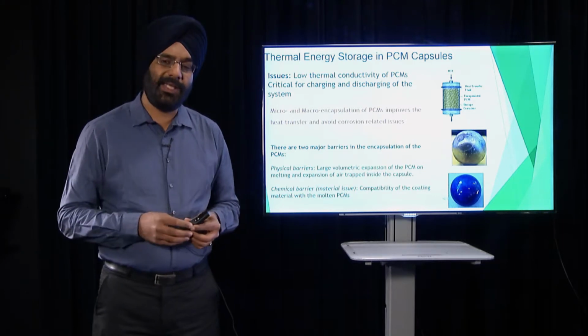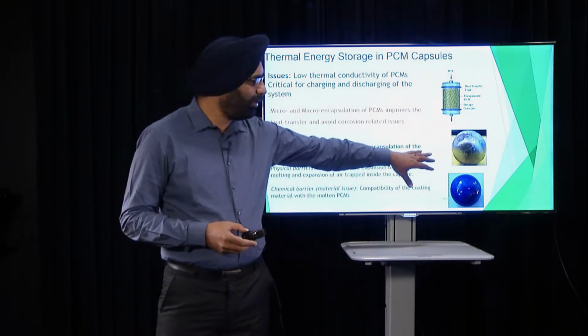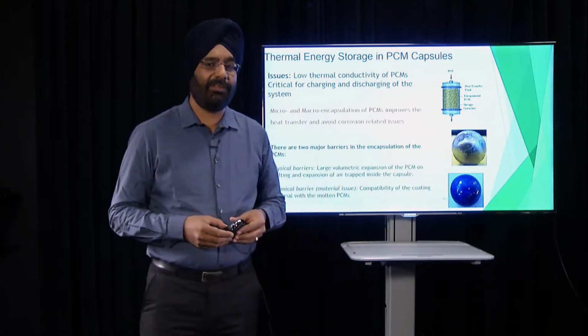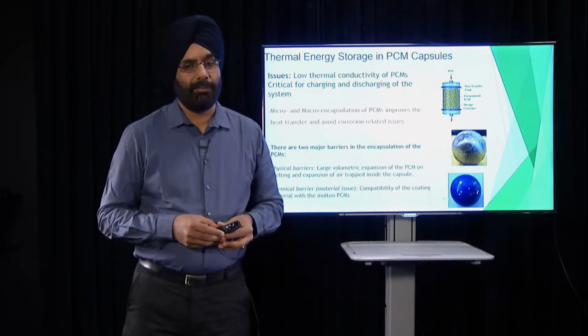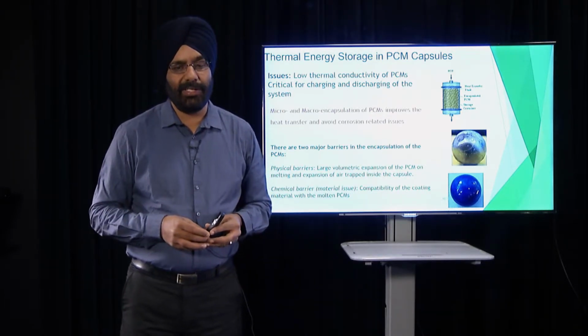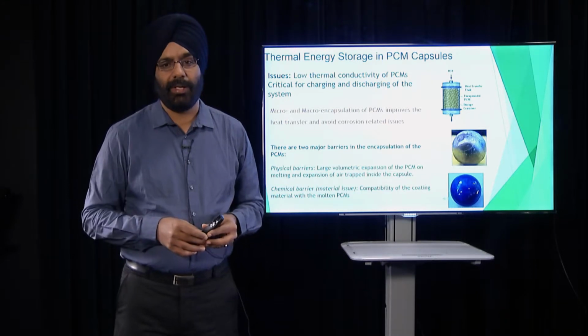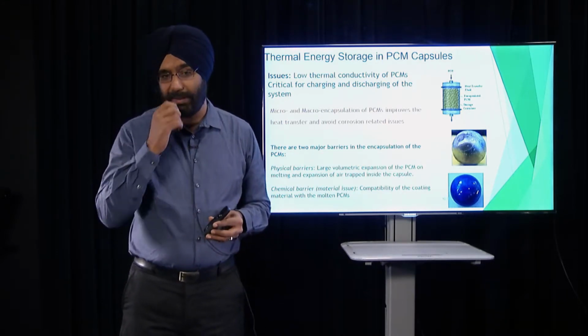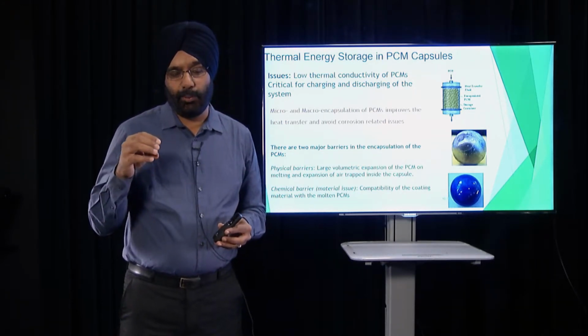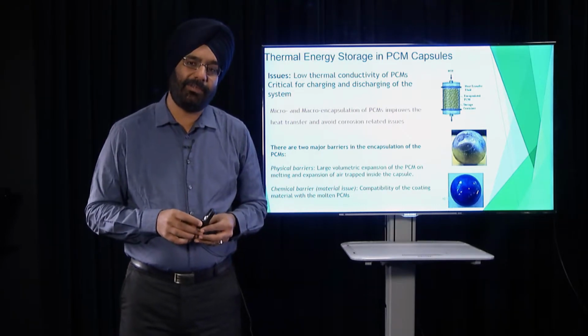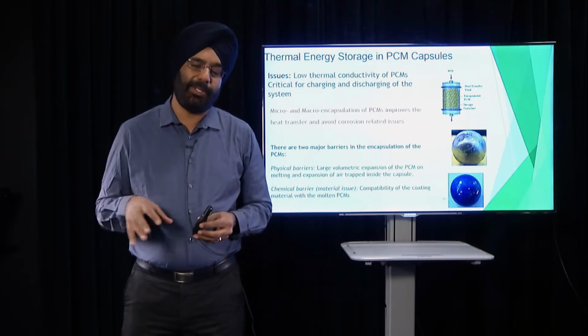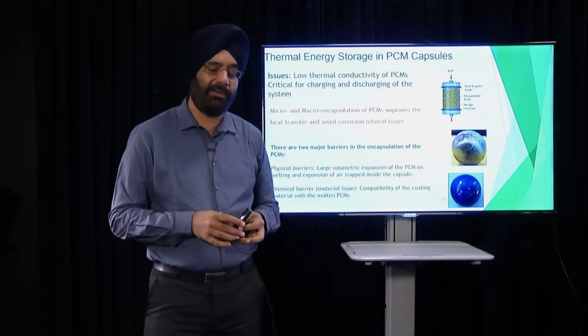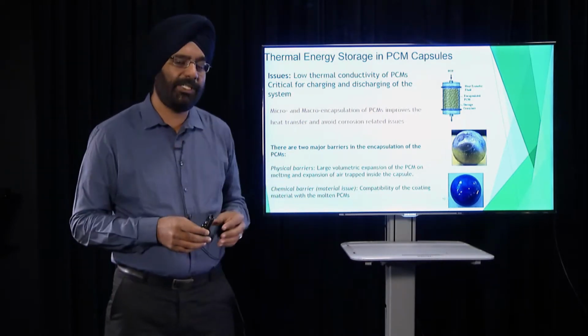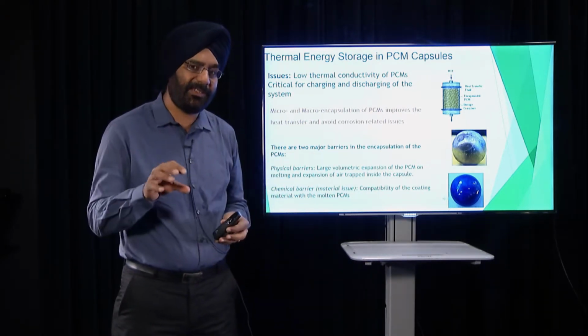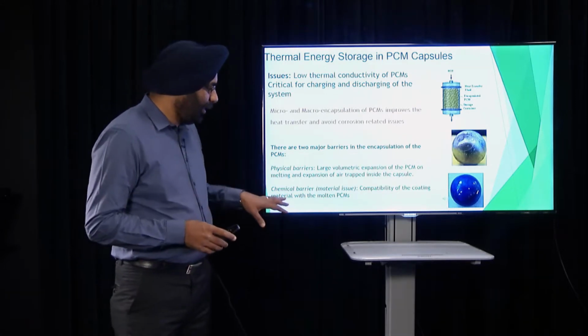So how do we contain that pressure? You should not increase the thickness of the coating, because that increases the cost, and it increases the thickness of the coating compared to the PCM, so that decreases the rate of heat transfer. So you want the thickness of your coating to be as thin as possible.